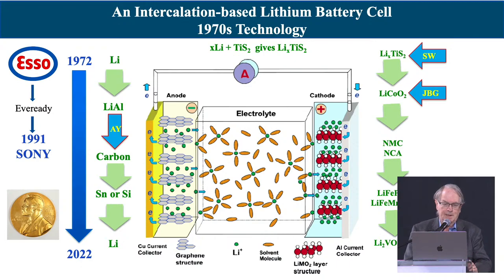John, about 20 years ago, also found out that lithium iron phosphate also enabled lithium ions to intercalate in and out in a reversible manner. But now you're carrying this heavy phosphate group, so the energy density is much worse. But this is a material that ought to be used for most grid storage because it's lower cost. So we want to use phosphates, they're safer. So let's put an element in there where we can now put two lithium ions or two sodium ions into the structure. So we've been looking at these vanadium phosphates.